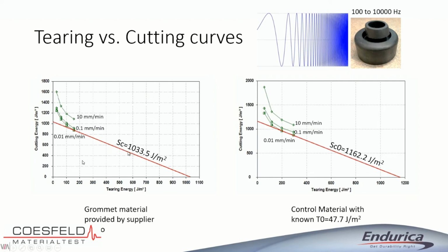In this case, that works out to a cutting energy of about 1,000 joules per meter squared. If you extrapolate these to the axes, you could say, well, the cutting energy here is 1,000 joules per meter squared, and so now this is a smaller number than the tear strength of the rubber, right? And the difference between those represents the dissipative part of the strength of the material. Or if you extrapolate this back to the y-axis, this would represent, if you could somehow eliminate friction and eliminate any contribution of opening the crack, the energy that it takes to push the blade through the rubber in a frictionless manner. So that's kind of what this curve represents.